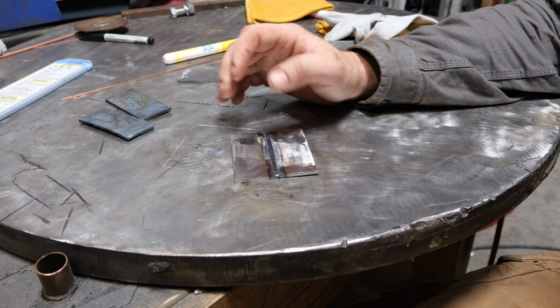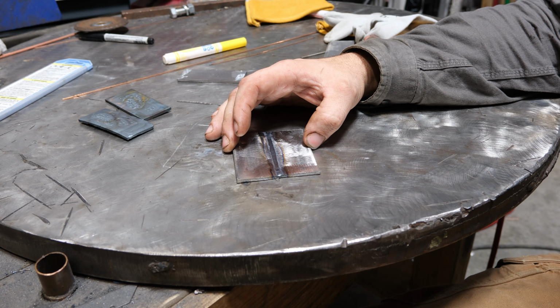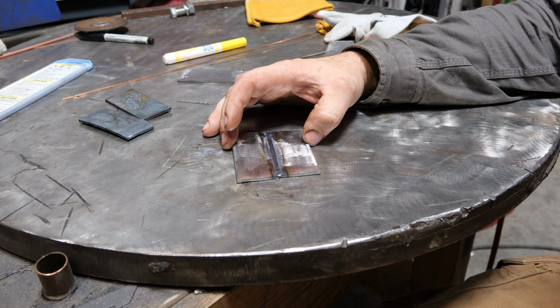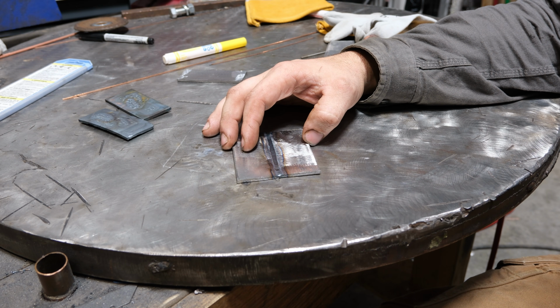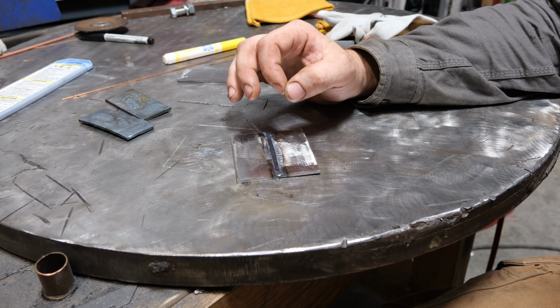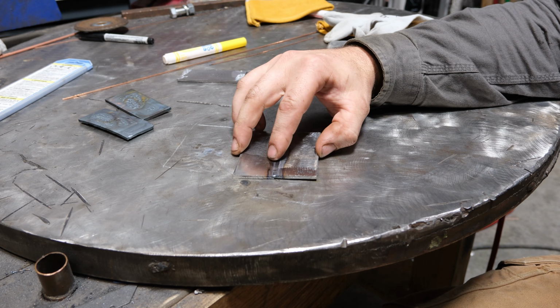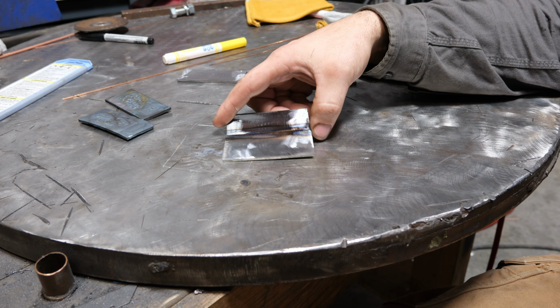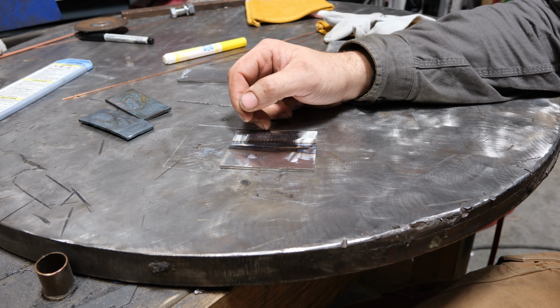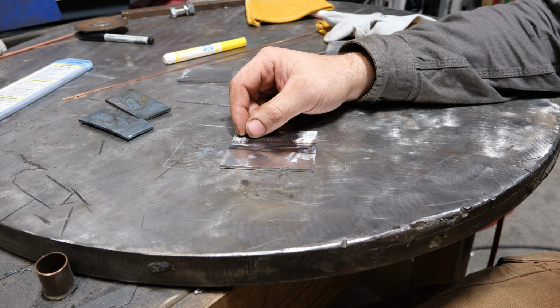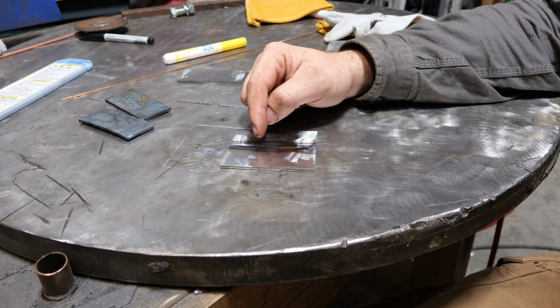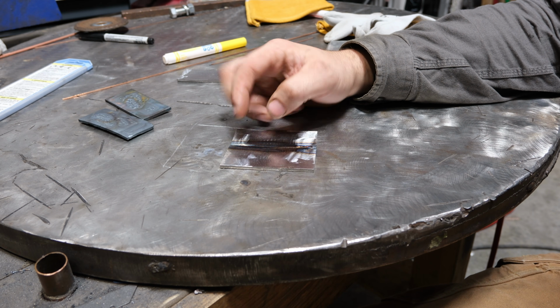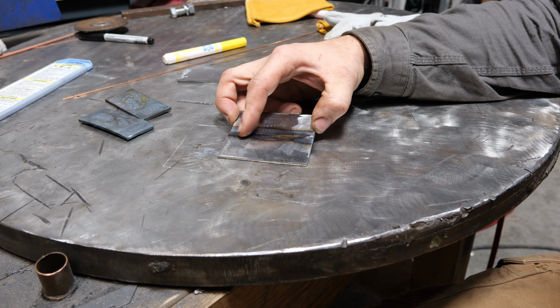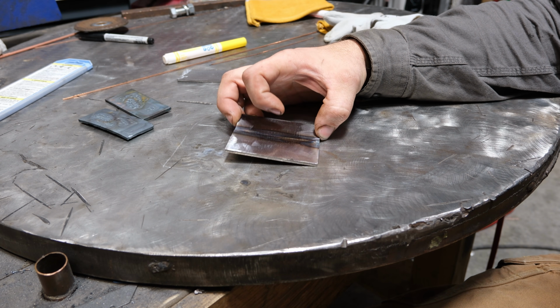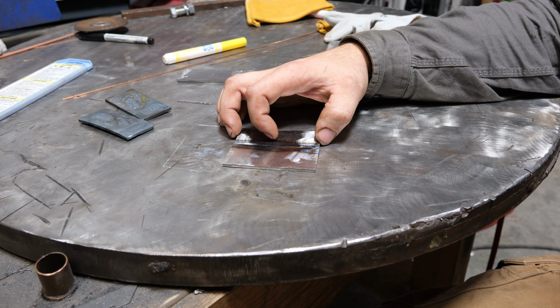And that is why doing something like 1/8 inch material as a fusion weld is kind of not really in your best interest on a butt weld like this, because there simply isn't much attaching these two plates together. Case in point, the back of it. Because I didn't run a gap and I wasn't running anywhere near enough amperage, there is zero penetration through these plates. There's a completely original edge there, and that is to be expected.